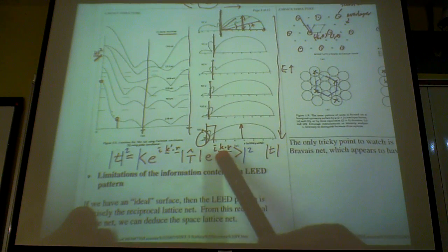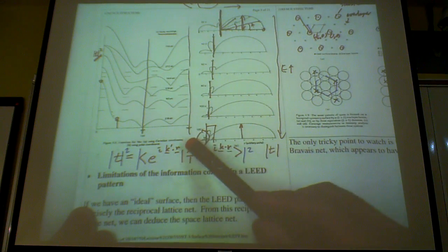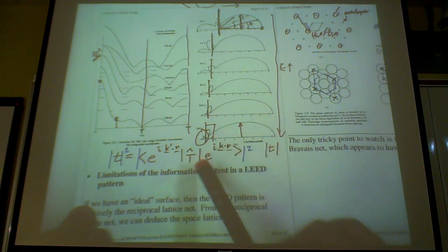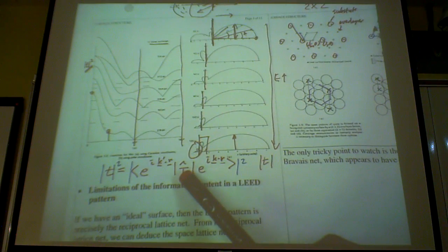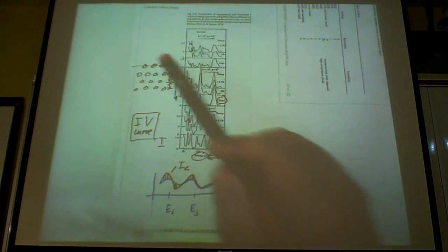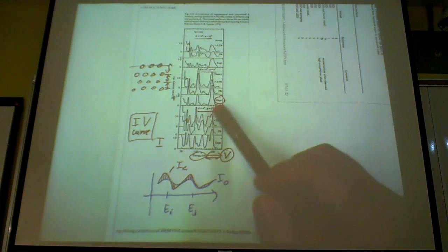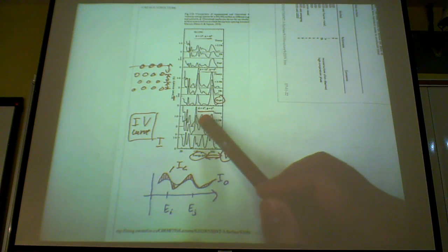The scaling is still a plane wave scaling, but this contains all the potential that you have, based on the model that you got. So this is where you input the model of this physical thing, and then you calculate this transfer matrix, and then you can determine the intensity as a function of energy. In other words, you use some theory. You calculate this curve.